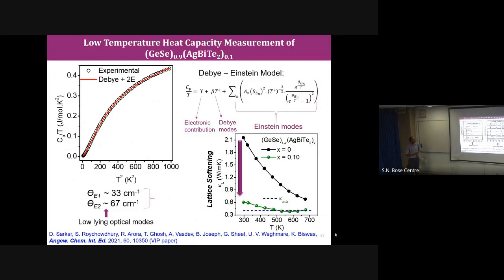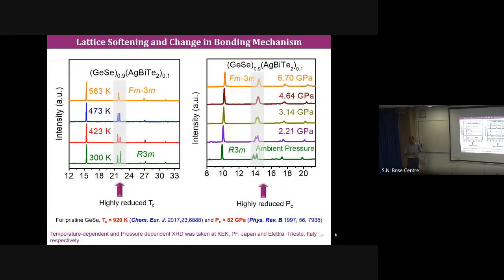Okay. So then, we have done high pressure X-ray diffraction as well as high temperature X-ray diffraction. As the bonding is soft due to this metavalent bonding, we should expect this R3 bar structure to go to the Fm3 bar m structure at lower temperature. But GeSe goes at around 920 Kelvin, while we see the transition happens around 500 Kelvin. At high pressure, the transition happens around 4 GPa. What is predicted is it should happen at 82 GPa for pristine GeSe.